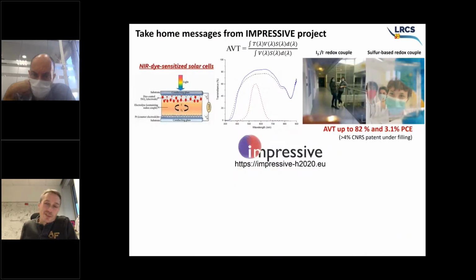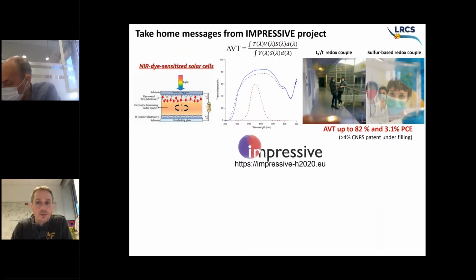I will end up here with the science, and I will summarize where we are actually with Impressive and give some take-home messages from the project. For the near-infrared dye solar cell, our main problem is really the aggregation, which reduces AVT and reduces the power conversion efficiency of the devices. However, either with iodine iodide redox couple, which gives a slightly orange coloration, or with sulfur-based redox couples, especially with these devices, we've been able to reach an AVT of 82%, which is really excellent. But unfortunately, the PCE is relatively low, 3.1%.